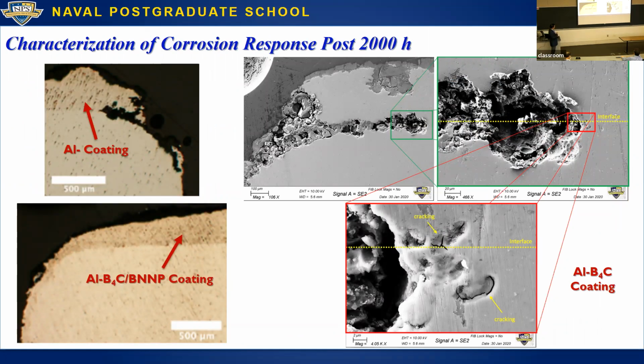You see here, this is the coating material on top, this kind of slightly darker phase. And this is the pure aluminum coating. And then this is the coating with actually both boron carbide. It was there mostly for strengthening and also to help with the dispersion of the BNNP. That was one of the synergisms that we were trying to get. We were trying to get the boron carbide to actually lay in between the platelets and help keep them from agglomerating together.